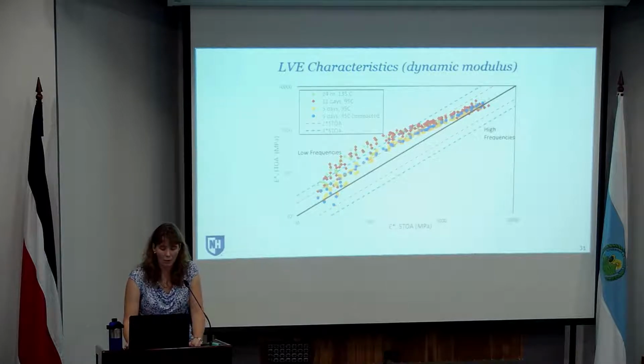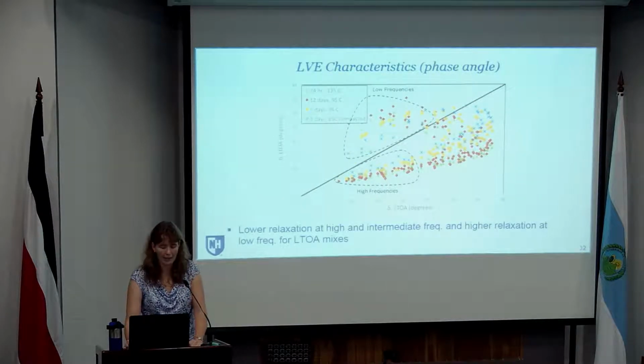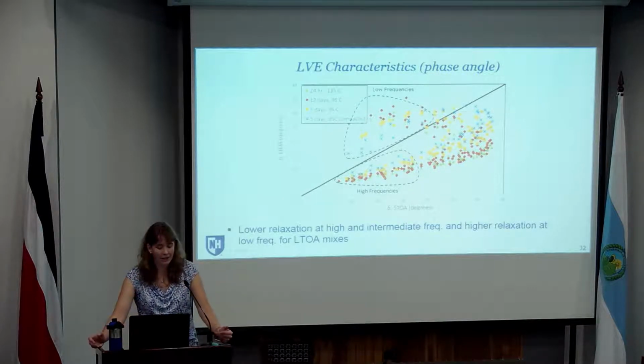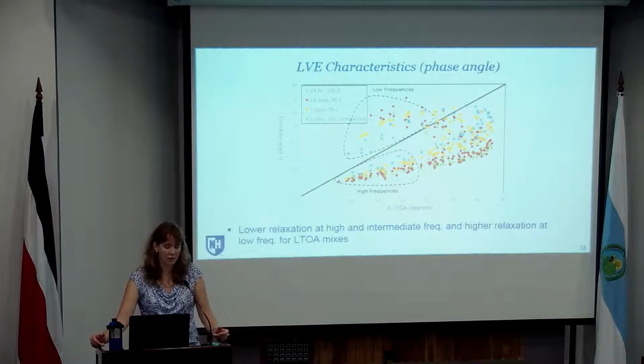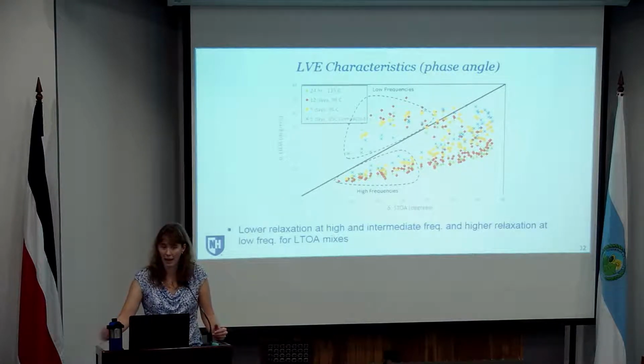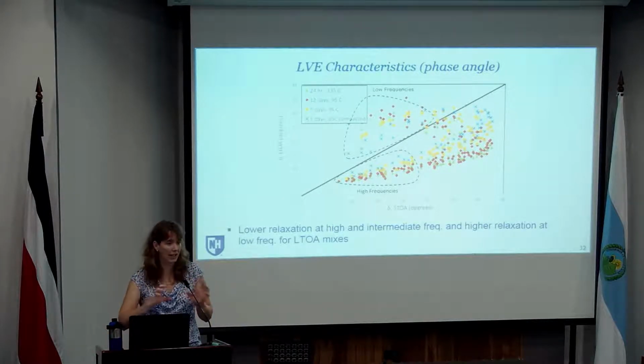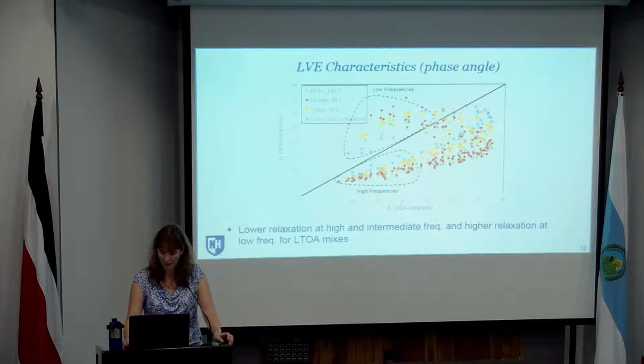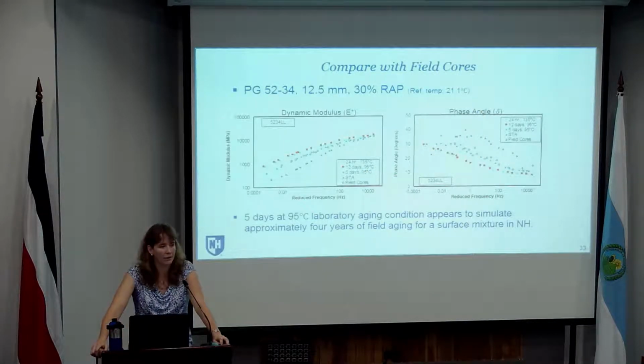Doing the same thing for the phase angle, looking at how that phase angle changes with aging with respect to the short-term condition. Again, you can see, looking at those high and intermediate frequencies, you've got lower relaxation capacity and then higher relaxation capacity at the lower frequencies as we increase the long-term aging. So again, it's important to understand how those different things are changing as the material is conditioned, or as it is aged.